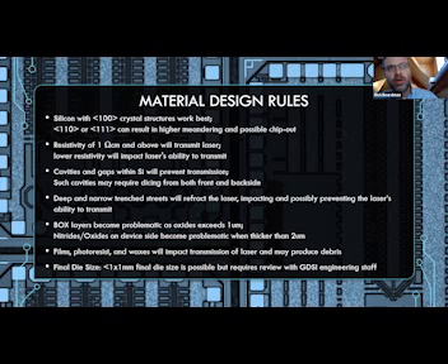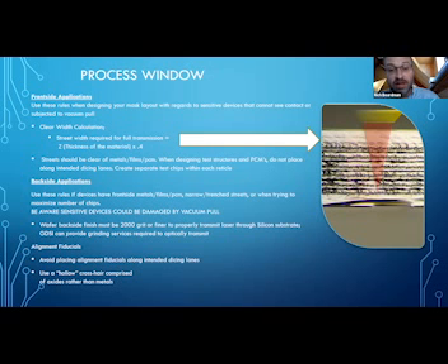So at that point, we are able to turn the wafer over if the backside of the silicon has a suitable surface. And what I mean by that is finer than a 2000 mesh ground finish. So that's right around 200 angstroms of roughness. What we are able to do is concentrate the laser light from the backside, put our modification layers in. We've already aligned from the front side features, which we've looked through with the IR camera, and then we're able to process and do die separation successfully.